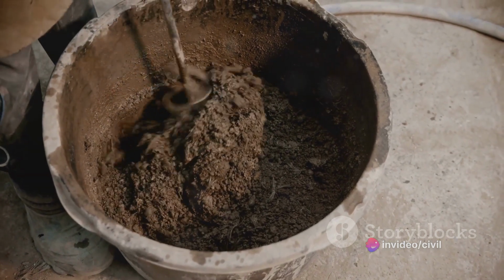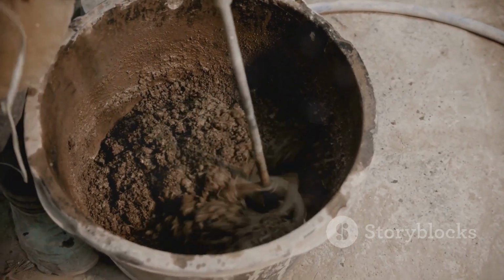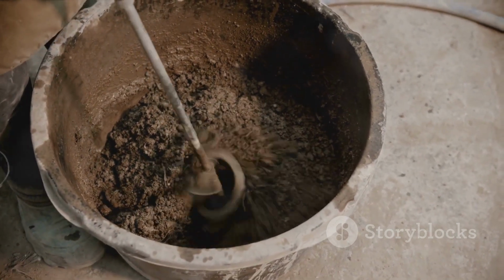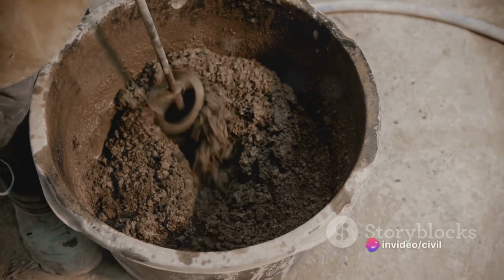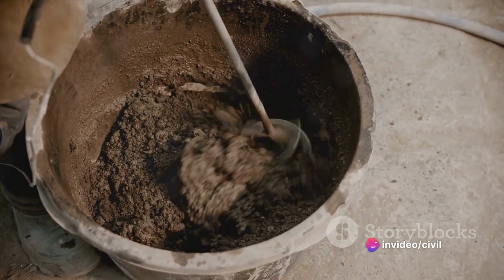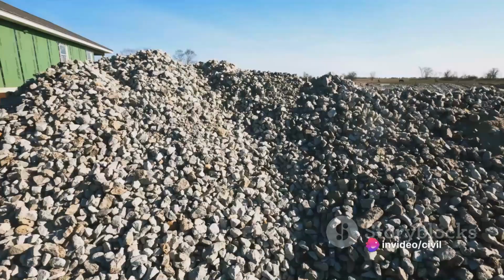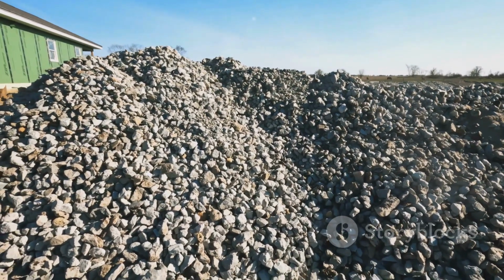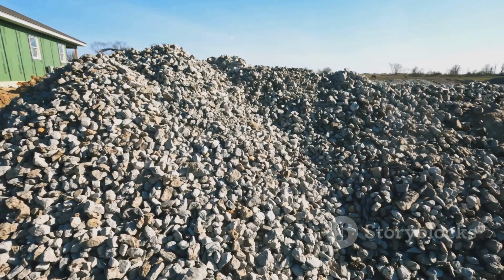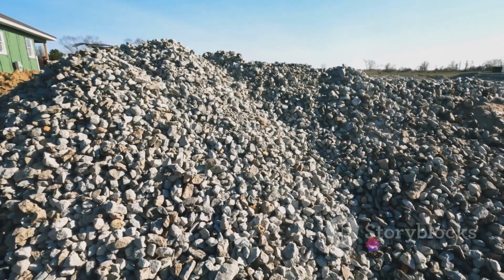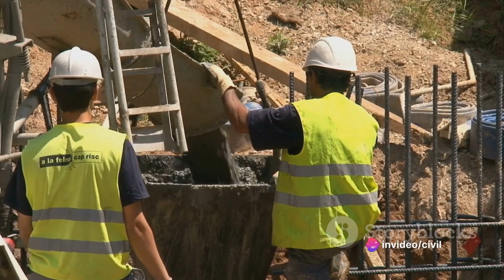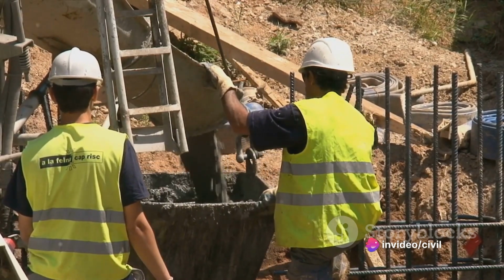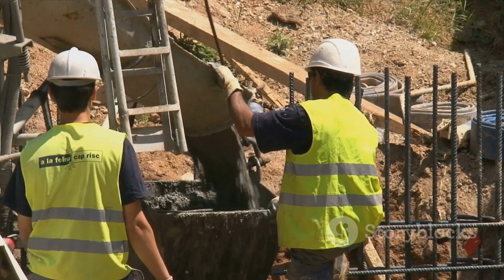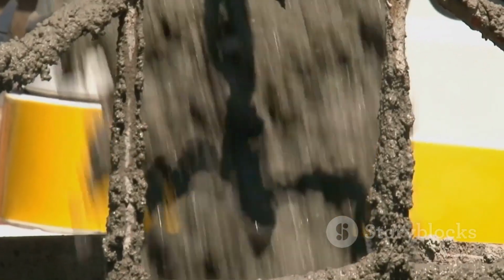Secondly, an incorrect or inconsistent mix of concrete can also cause honeycombing. If the mix is too dry or too wet, or if the aggregates are not well distributed, it can lead to a poor quality concrete that is prone to honeycombing. Thirdly, the use of large aggregates can cause honeycombing. While larger aggregates can increase the strength of the concrete, they can also create voids if not properly dispersed. Lastly, improper placement of reinforcement bars can also lead to honeycombing. The bars should be placed in such a way that the concrete mix can easily flow around them, filling all spaces and avoiding any air pockets.